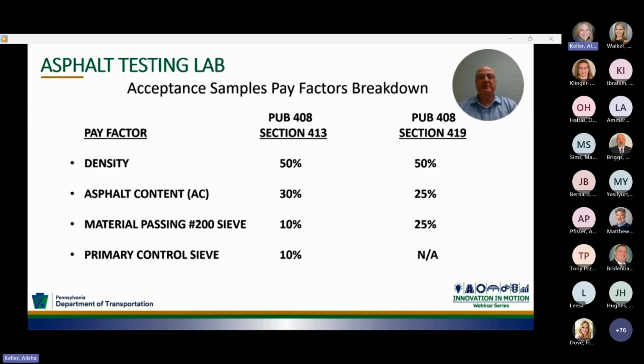Section 413 specifies the Superpave mixtures, and Section 419 specifies the stone matrix asphalt, also known as SMA. Density is 50% of the pay factor for both sections, and it is followed by the asphalt content, which is 30% for Superpave mixtures and 25% for SMA. Then a 10% pay factor is counted for the fine material that passes the number 200 sieve for Superpave mixtures. This pay factor is 25% for SMA. Finally, the last 10% pay factor for the Superpave mixture is determined by the primary control sieve.